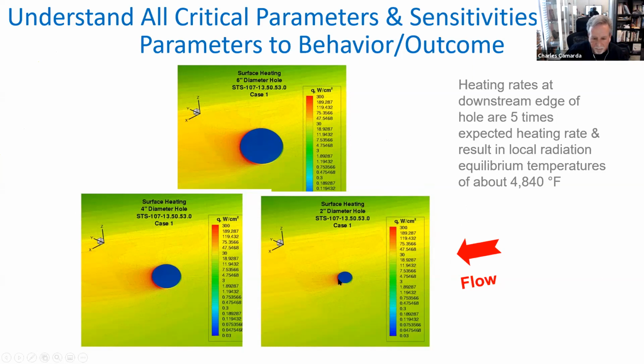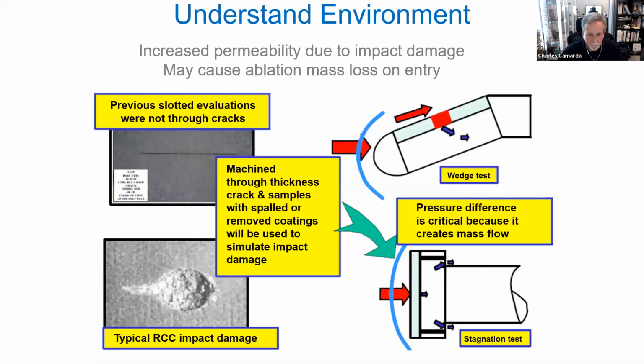And what you see as the flow strikes the downstream lip of that hole, the heating there is very high. And so what this means is if the flow is at an angle to the vehicle, you have much higher heating in the downstream lip. This will determine how this hole grows, how fast it grows, and so it gives us some idea of the limitations or what size hole could potentially cause critical damage.